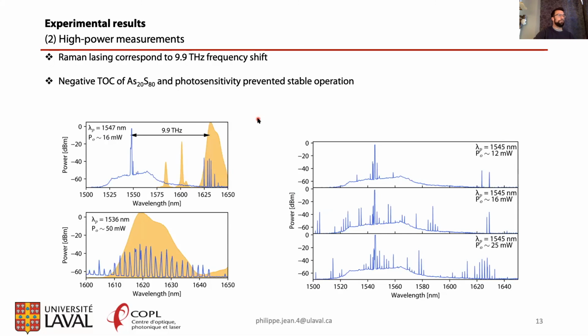Okay, and finally, the most interesting part, I guess, of this work: following the fabrication and the relatively good quality factor we achieved, we explored the possibility of using these resonators as either Raman lasers or optical parametric oscillators. And you can see here the result. The first thing I want to mention is that the glass photosensitivity, as well as the negative thermo-optic coefficient of As20S80, actually prevented us from having thermal locking and having stable operation and doing more characterization of these microresonators.